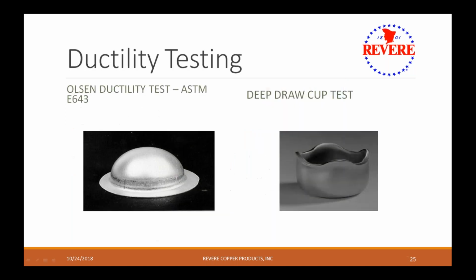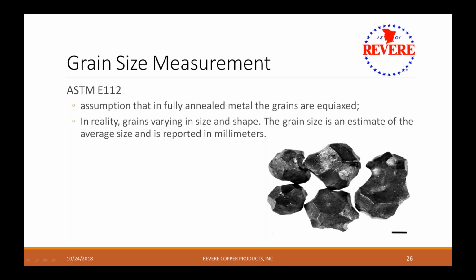We also do a ductility test. That's just to confirm that it meets the properties required for being deep drawn. This would be for metal that's ordered soft. And also for soft metal, we'll do a grain size measurement. And with the grain size, we're basically looking at it under a microscope, and the average size is reported in millimeters.